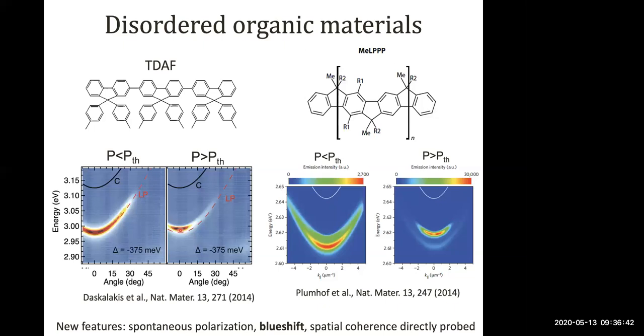For condensates, there's also a different case, which is, for example, our work on third harmonic generation, where there the chi3 is really due to the intrinsic chi3 of the bare material, but not due to a bleach of the resonance. But here, near resonance, the dominant contribution is coming from the ground state bleach. I'll come to that in a few slides.